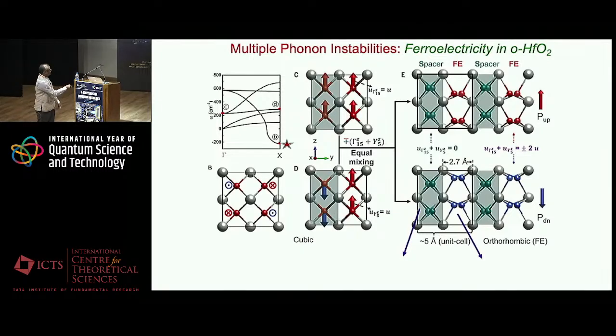And what we find is that the only instability in cubic hafnia involves antipolar displacements of these oxygen chains. These, of course, will not give you an electric dipole moment because half of the negative ions go one way and the other half go the opposite way. But they couple beautifully with these two phonon modes. This is the polar mode, which is this, and this is the antipolar mode, which is here.